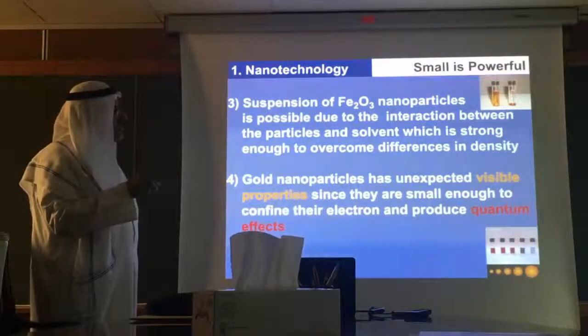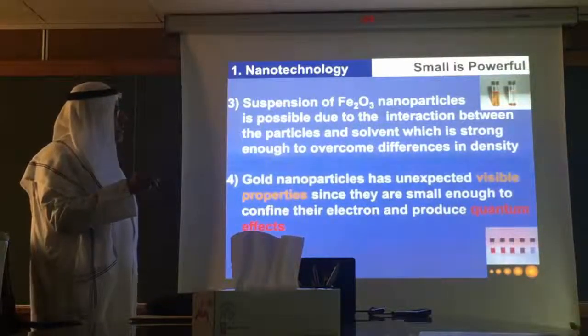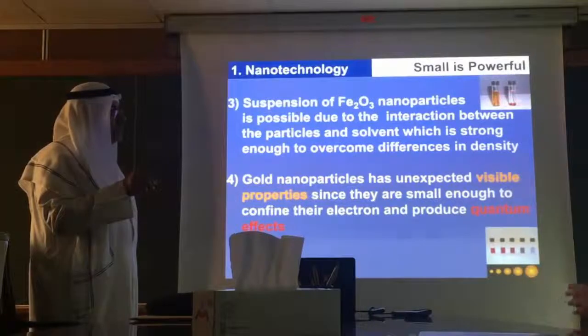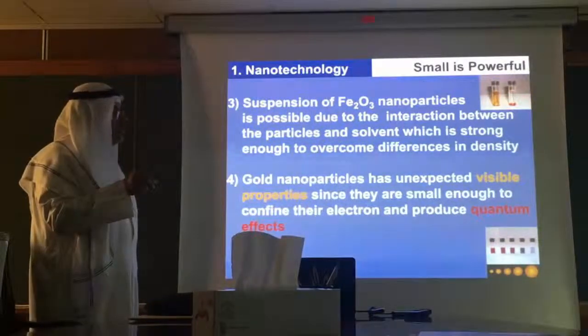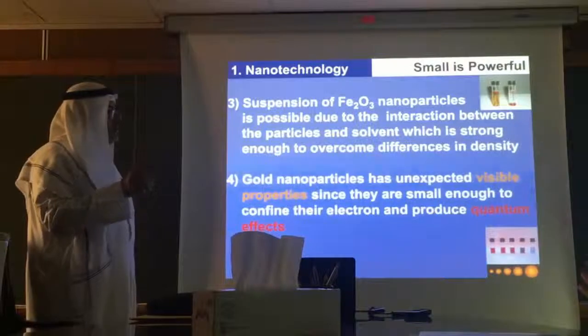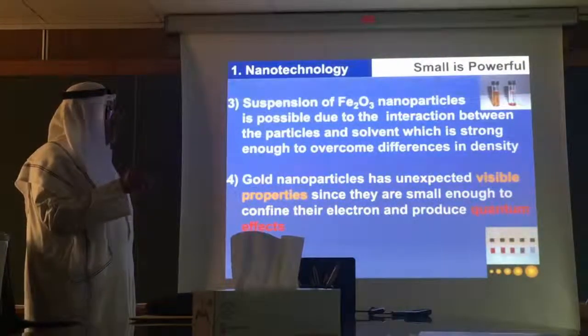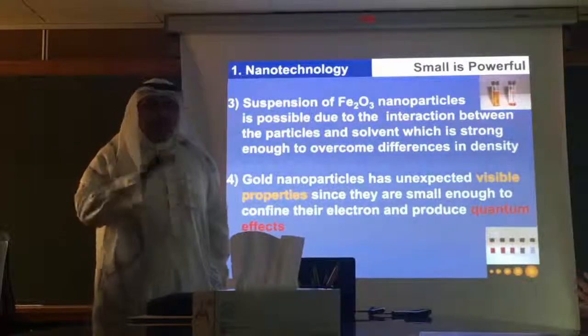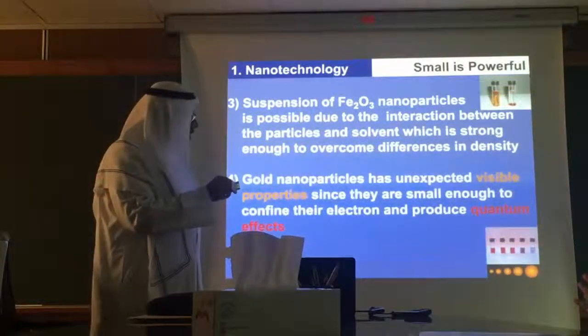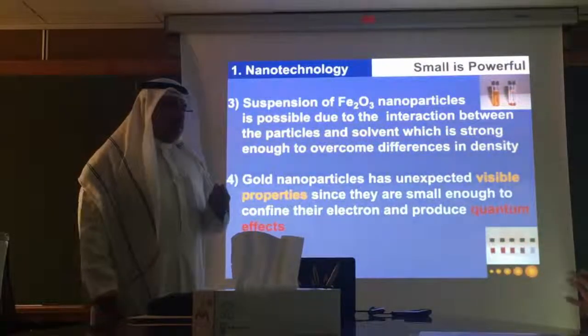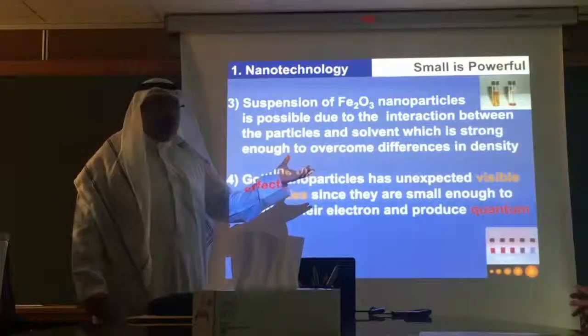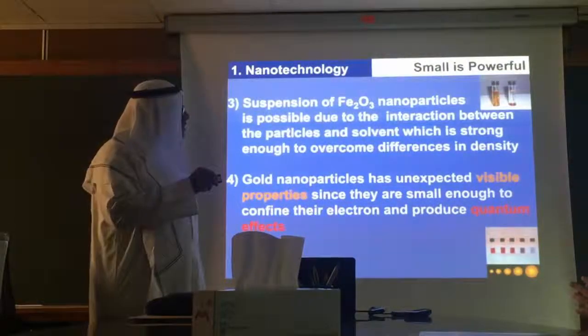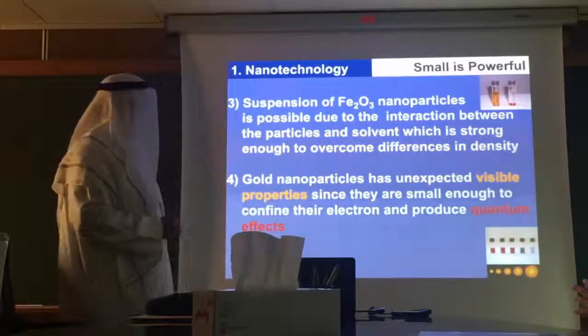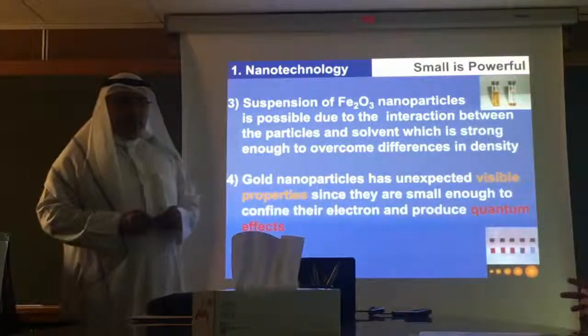This is a suspension of iron oxide nanoparticles, and this is also a suspension of iron oxide particles with larger size. You can see here it's very difficult to disperse, while here it's completely dispersed, and it's actually colorless, transparent. The particles are so small that they don't even scatter light. The color here because of the iron oxide is reddish or yellowish, but you can see through it because of the smaller size. So when you have smaller particles, you can enhance the stability of the suspension.